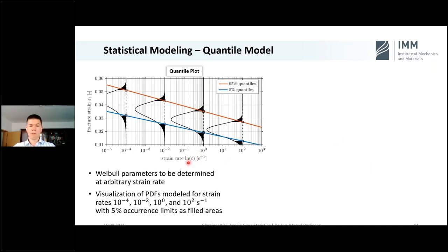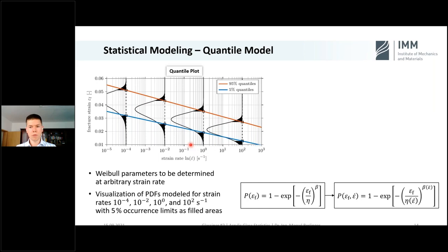What does that mean? We take these regression lines and go into the next diagram. Here, for four exemplary strain rates, here, here, here, and here, we are cutting our two regression lines. So for the first we get the 5% quantile, and for the second the 95% quantile. And thus, these are two points of our two-parameter Weibull distribution. And as the name indicates, we only need two points to define the two parameters of the Weibull distribution. And so here in black symbolized is the Weibull distribution corresponding to these 5% and 95% quantiles.